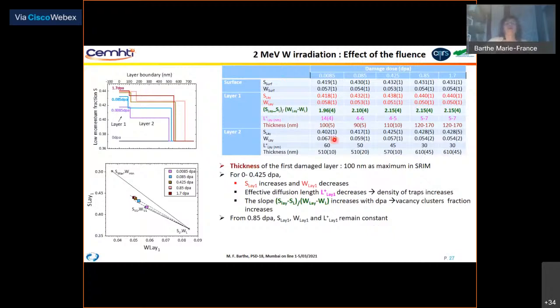And we extract from this fit the different data corresponding to the S and W in the layers, the ratios S layer over S lattice and W layer over W lattice, and also the effective diffusion length. We can see that S increases and W decreases in this first layer. The effective diffusion length decreases, which means the density of traps increases, and the slope also increases with dpa. You can see here from 1.96 to 2.15, indicating that the vacancy cluster fraction increases.